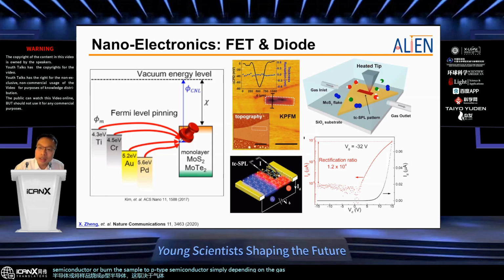If we flow inert gases, we can dope the sample to an N-type semiconductor. If we change to another gas, we can dope the sample to P-type. So here, it's easy to convert a channel to a diode, consisting of half P channel and half N, and we have achieved a 10 to the power 4 rectification ratio on a monolayer TMDC. These are good results from my postdoc.